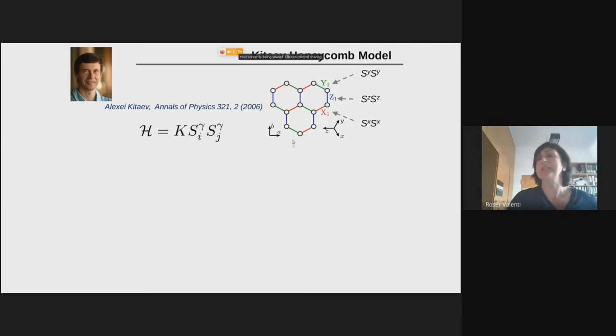You take, for instance, a honeycomb lattice, and now you define an Ising coupling, a nearest neighbor Ising coupling, but this nearest neighbor Ising coupling is bond dependent. So that means if I am in this X bond, the coupling is going to be σx σx. If I am in the Z bond, it's going to be σz σz. If I am in the Y bond, it's going to be σy σy.